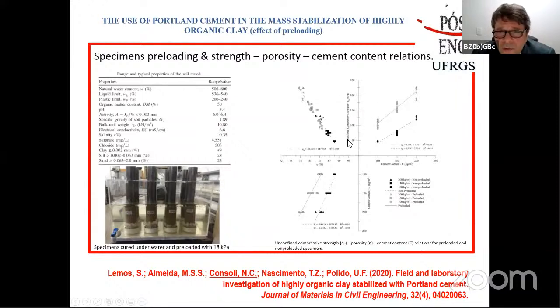So if we plot the unconfined compressive strength that is linked to these amounts of cement, without preloading and with preloading, versus the porosity that you have measured, we can see that in the end you get to a unique trend here. However, the results without preloading are quite below the ones with preloading that are here on the top. So you get much stronger strength using the preloading. So it's quite interesting to analyze such a thing and to get to such results.